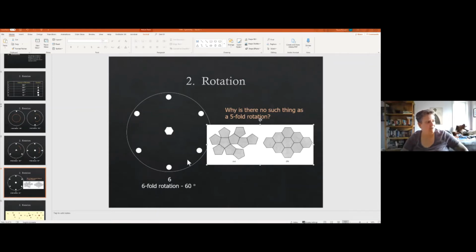So if we look at this triangle here, we see A, B, and C. B goes through the inversion point and becomes B prime. A goes through the inversion point and goes to A prime, and C goes to C prime. The difference is, if this was a mirror plane and we put a line through here and mirrored this to this, B and B prime would be the same, but this would be A prime and this would be C prime. So there's a difference, even though it can kind of look the same. Where the atoms wind up are quite different between an inversion and a mirror plane.